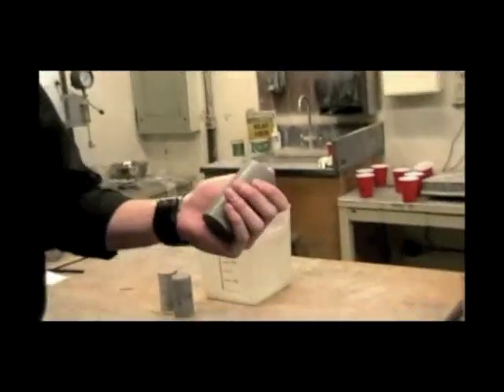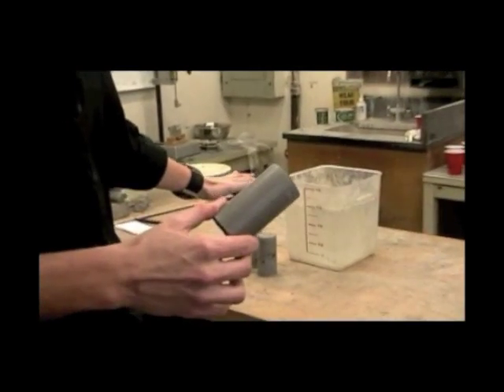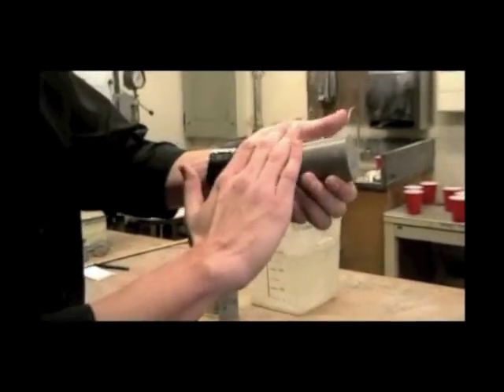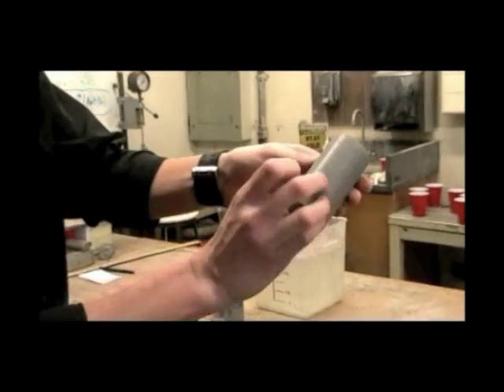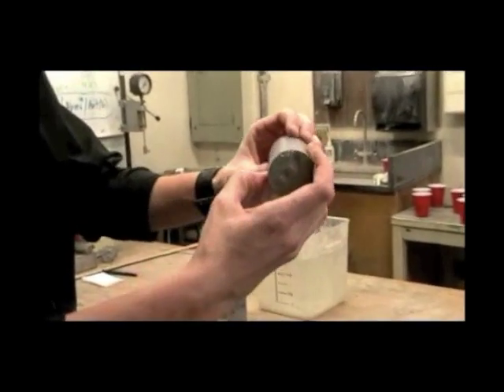Through testing and observation, we decided as a team that mix 3 would be the baseline mix with a few adjustments for the final concrete canoe mix. By observing mix number 3, it's slightly heavier than the other two, but it's got a nice smooth coat, air voids are minimized, and it is extremely strong.